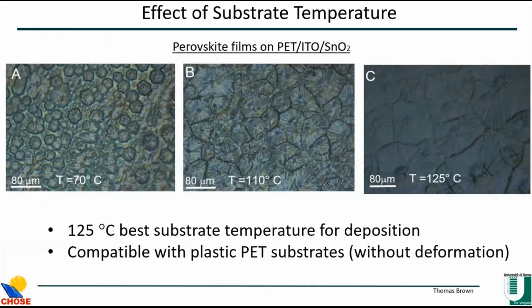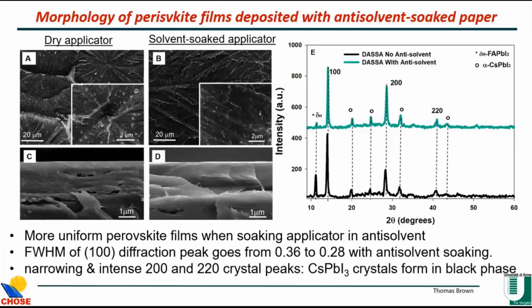Also, we did a study in which temperature was best. Now for PET, you can only go up to 125 degrees, otherwise they deform. And actually 125 degrees, again, macroscopically, the film uniformity was better and compatible with plastic substrates. We then did, more microscopically, high resolution microscopy.